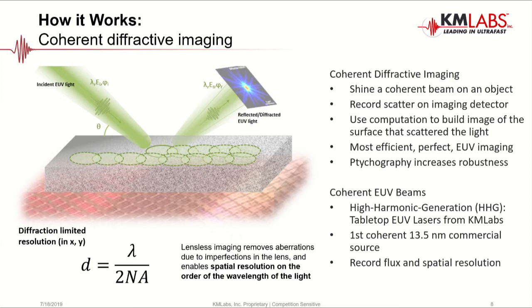And when we reconstruct that, we can then bring it back into real space and get what we're expecting more intuitively, an actual image of the features on the sample. And as I mentioned, because we're not using a lens here, you notice there's no lens between the sample and the detector, we can get essentially wavelength limited resolution, or diffraction limited resolution. So we're going to be able to get spatial resolving power that's more or less equal to the wavelength of the light. In some cases, maybe even a little bit better.